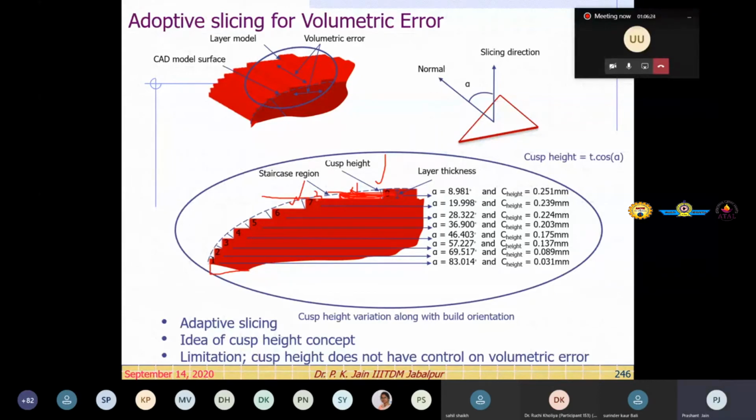Yeah, you are saying something? So I thought the nozzle would have to be changed or something like that. Yes, that is the point. That is the reason. Suppose instead of 200 micron, you said 175 micron. You can manage it by moving at a faster rate, right? Or suppose you are saying 200 to 100 micron. This is not possible. In that case, you need to change the nozzle.